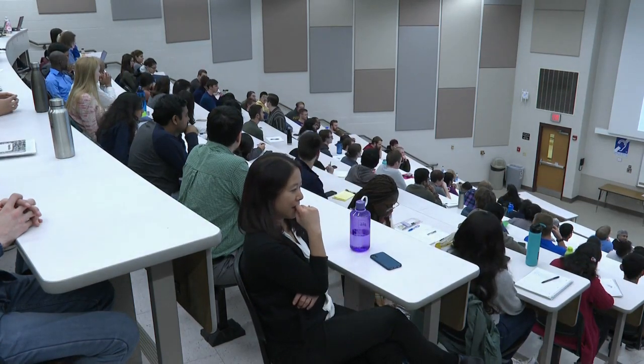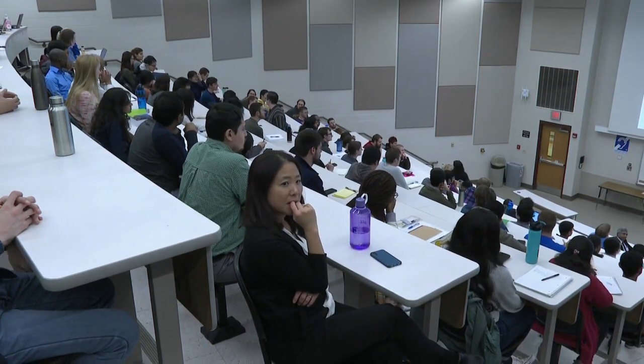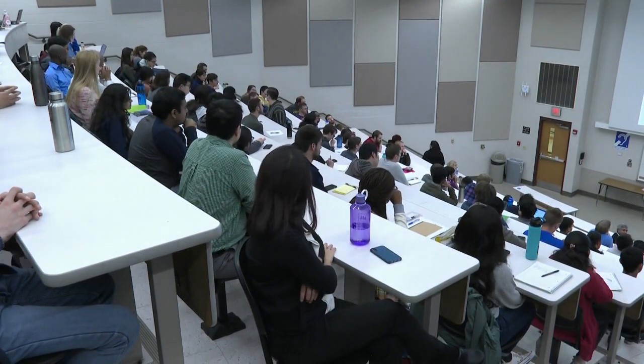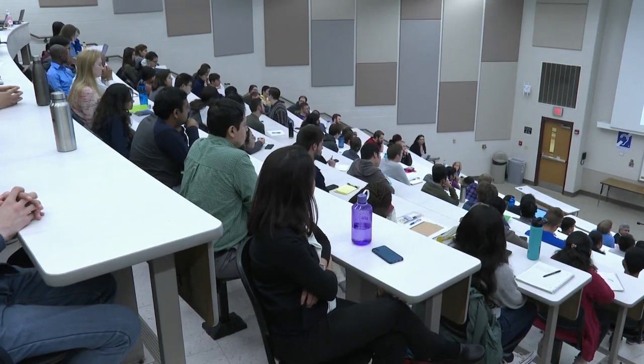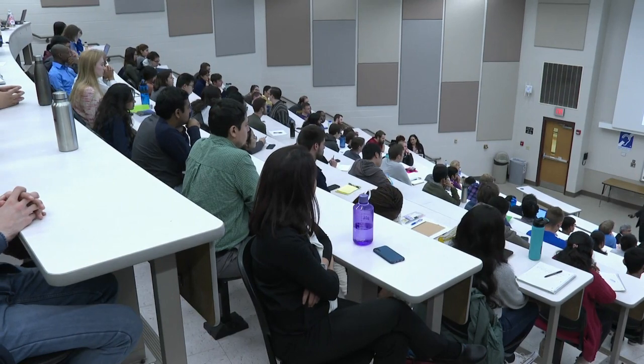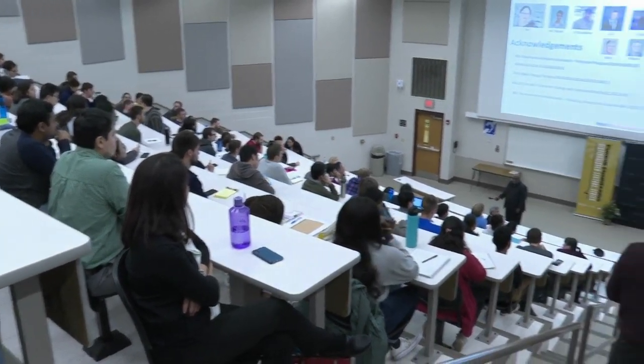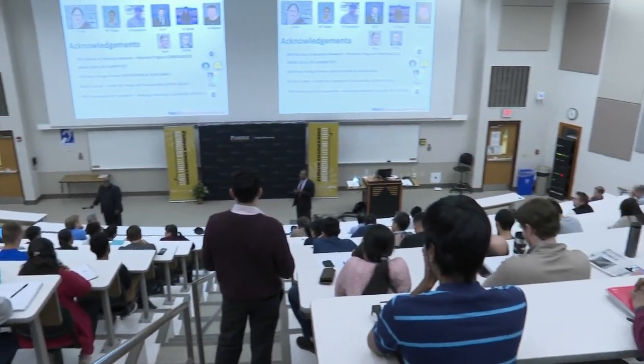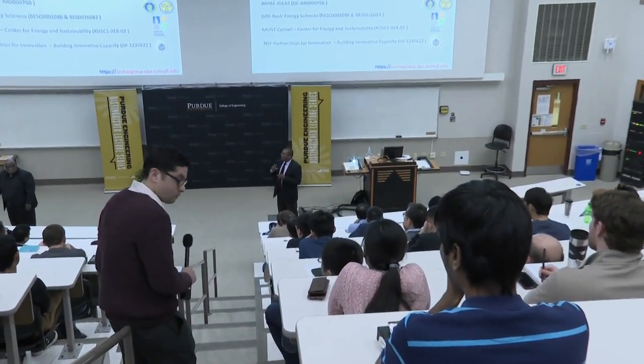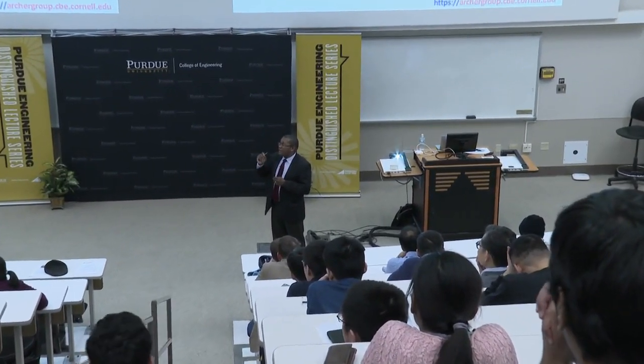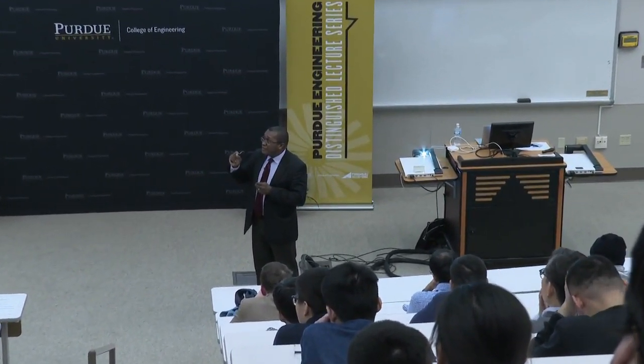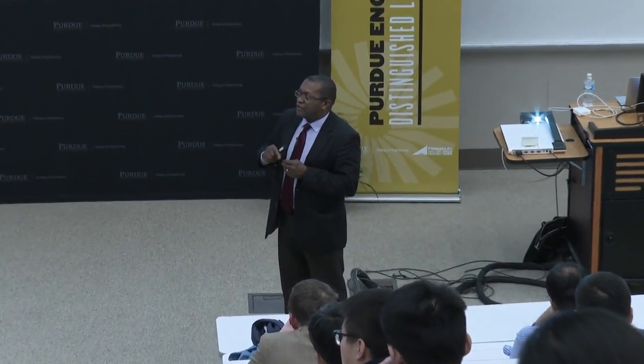In case of the turbulent flow beyond the current regime, does the counterflow originate from the movement of the counter ion? And if so, does the transference number have an effect on the turbulence? That's a great question. The flow actually results from the coupling between the concentration of the active ion and the electric potential. The counter ion enters because electroneutrality would want the concentration of the counter ion to be everywhere equal to that of the active ion, which in this case is a metal ion.